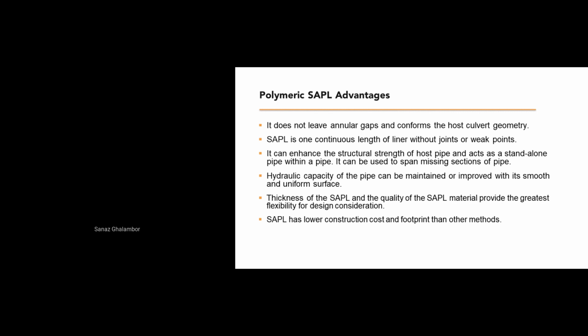And comparing to CIPP, it doesn't need large amounts of pressurized water to be installed or a boiling system to be cured. Actually, the curing process is not separate from installation. So when we spray the liner, as soon as it is in contact with the substrate, it starts getting dry and cured. So no separate step for curing. It is environmentally friendly, chemical resistant, and it can be applied very fast.